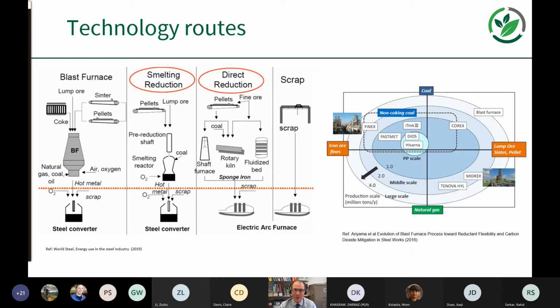Then we have the direct reduction, which uses iron ore directly with gases. They could be syngases or hydrogen possibly, or coke oven gas, and there are very well established technologies in place in the industry for producing directly reduced sponge iron. So in the solid form, it's a lower temperature. That's why the energy emissions associated with it are lower. It tends to be used to improve the quality of the final product from the electric arc furnace. And then, as we described previously, we've got scrap-derived steel production from the electric arc furnace. And we'll cover some of these in a little bit more detail later.